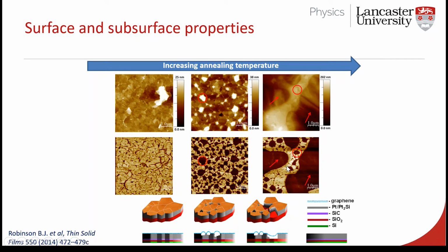And the way to interpret these images now is along the top, the brighter it is, the higher it is, the taller it is. Along the bottom line, the brighter it is, the stiffer it is. So what you can see here, for example, is we have these high regions by this red circle correspond with things which are very, very soft. And in this image here, we have these big sort of plateaus of material, which are very stiff. But then we have sort of membrane sheets of materials at the side, which are very soft.